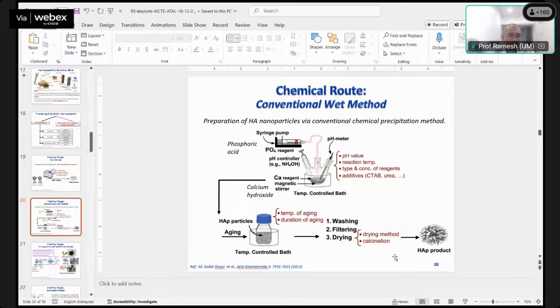And then we also have the conventional wet chemical method. When we look at the wet method, this is very straightforward, the chemical precipitation method. I am one of the early pioneers in this method. This has been done for almost 20 odd years, 25 years ago. It's very simple. All you need is a calcium agent. Most of the time we use calcium hydroxide. We dilute it in liquid, and then we take phosphoric acid, dilute it in liquid, of course, at a certain ratio. And this is where the challenge comes in, how we control those ratios.